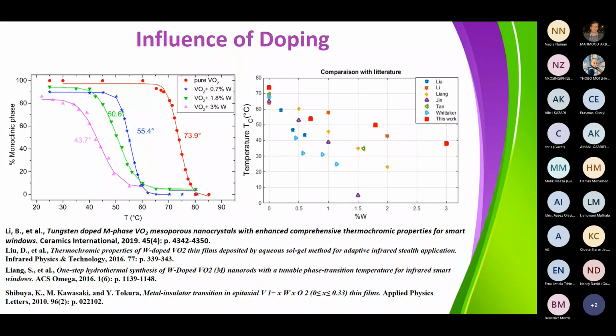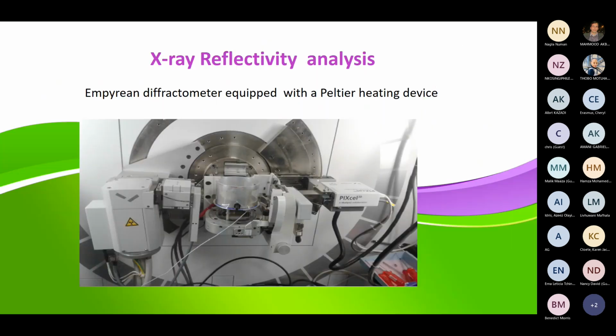If you look at the literature, you will find that people are observing very different variations of this transition temperature, depending on the tungsten concentration. I don't want to go too much into the details, but this is what we have found here. And then we did the reflectivity.